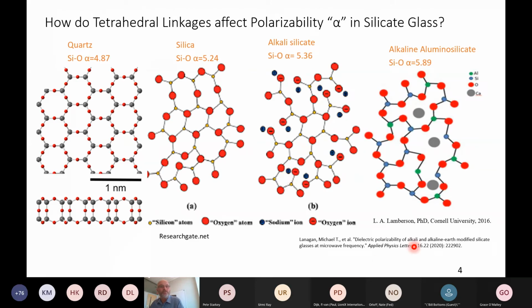Just a recent publication in Applied Physics Letters is shown here, where we compared, it's the same composition. Silica, remember, is just sand. It's silicon and oxygen. And so if you look at quartz, it has a very, very nice uniform structure on the molecular scale. You can see here the silicon are these little gray dots, and the oxygen are the little red dots. And then as we move from crystalline quartz to something that is glass-like, so fused silica, no impurities, you can see these nice little hexagons get a little messy, right? So now all of a sudden we may have extra atoms in there, and that provides a lot of wiggle room, so to speak, for this structure.